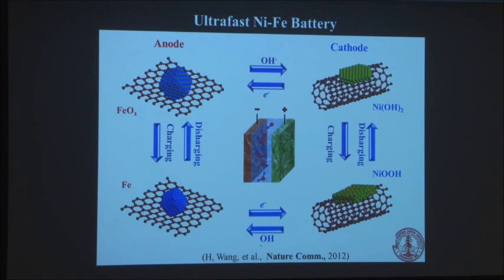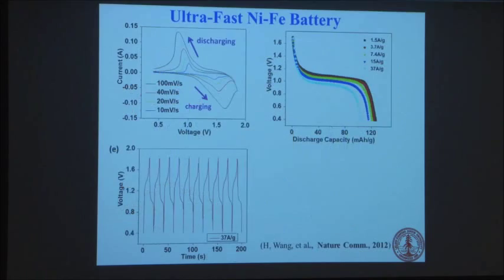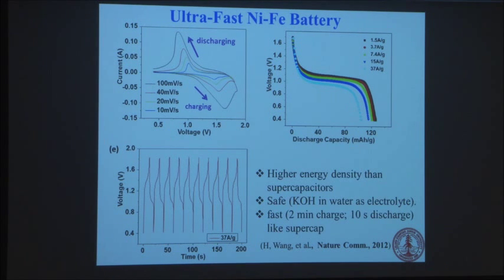So we made this battery by changing the electrode. We made nickel, in this case on carbon nanotube, and we made iron on graphene, and both of them can be charged and discharged quickly. Now we put them together and see how they perform. That's the discharge curve, and you see the voltage is about 1 volt because this is in aqueous solution. But the charge and discharge here is very fast, in a matter of minutes or seconds: a 2-minute charge or 10-second discharge.